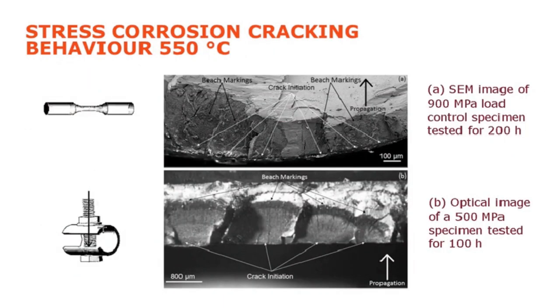So if we take a look at some experimental test results, these are a couple of images of statically loaded specimens. So there's no cycling here. These are cracks which have been generated in line with stress corrosion cracking rather than fatigue. And what we see is multiple initiation sites. The top image is of a plain cylindrical specimen, statically loaded at quite high stress, 900 megapascals. But we see multiple cracks initiate and propagate.